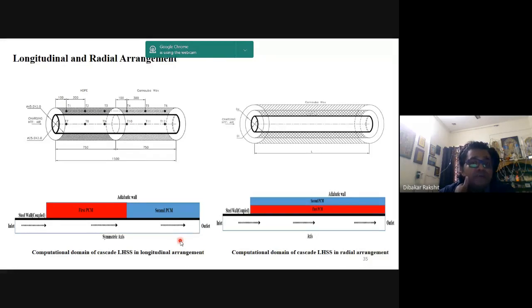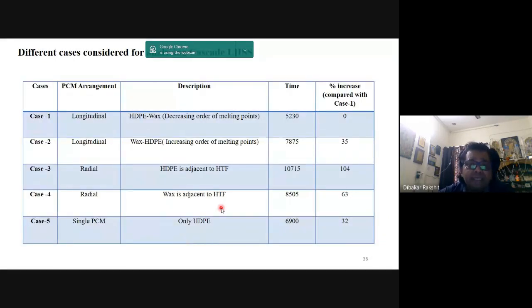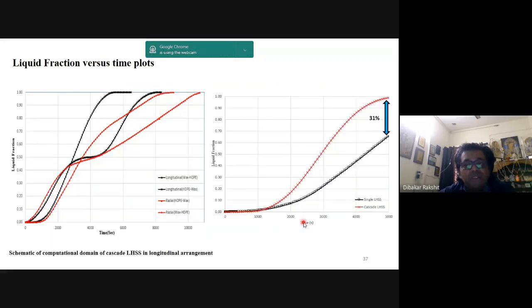Of course, cascaded systems are more stable as compared to a single PCM or single latent heat storage system. But we wanted to see how this can be affected if we arrange it in a different way. So we compared the utilization of HDPE first and then carnauba wax, in decreasing order of melting point, and the other one in increasing melting point, in the longitudinal as well as in the circumferential and radial manner. And then we utilized only one phase change material, similar to our previous studies, and found how the melting time is getting changed. So that was the observation which we found.